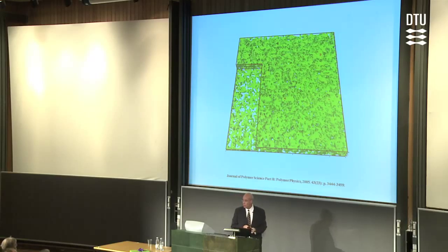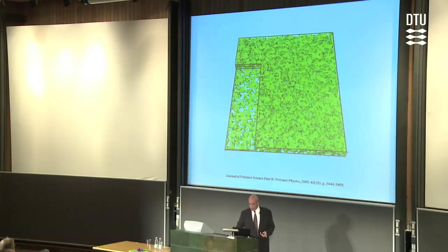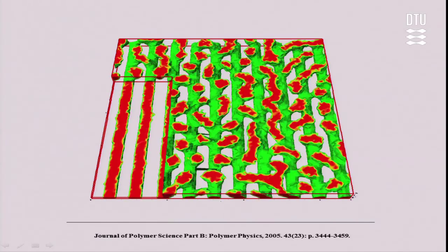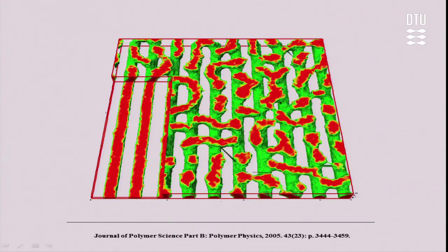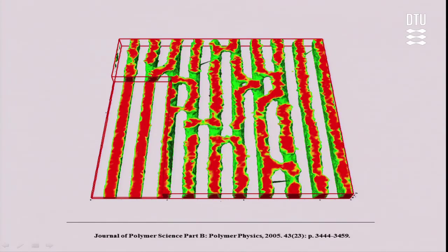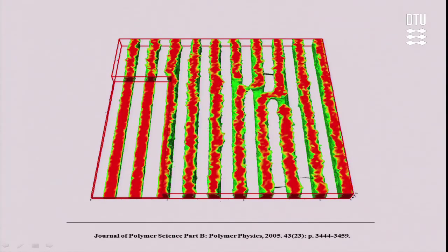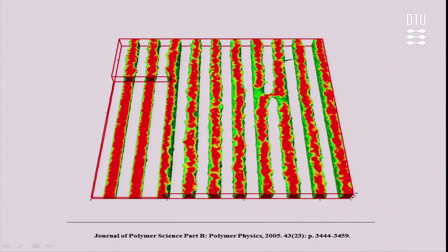All right? So now, this is how it works. Whereas before we had a tiny little piece of material using lattice simulations, just 2 lamella, right? Those simulations were tiny. Now we can go to these very large domains. We start with a disordered system. In green, you see the interface between red and blue. You see the stripes at the bottom. And then you see that as you lower the temperature, the system self-assembles into these lamella that follow the pattern on the surface. At the beginning, you have defects. But as time proceeds, you see that these defects disappear, and eventually you have perfect registration between the stripes on the surface and the lamella.